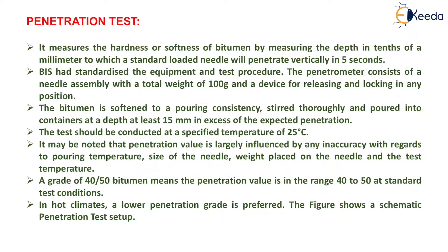Now we will start with the first test, i.e., the penetration test. It measures the hardness or softness of bitumen by measuring the depth in tenths of a millimeter to which a standard loaded needle will penetrate vertically in 5 seconds. The Bureau of Indian Standard has standardized the equipment and test procedure. The penetrometer consists of a needle assembly with a total weight of 100 grams and a device for releasing and locking in any position.